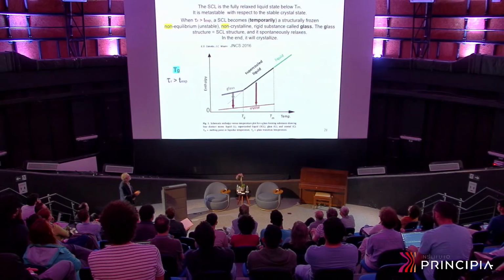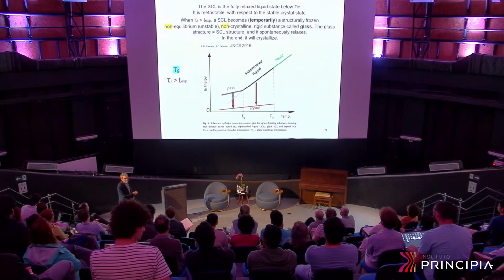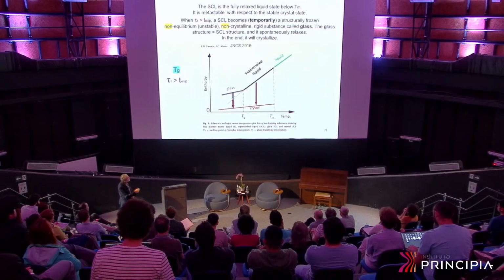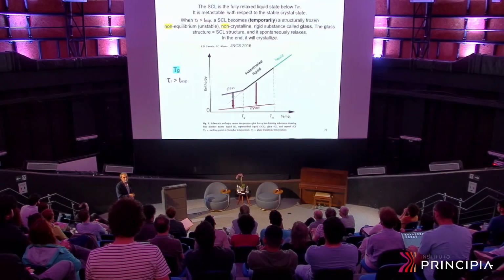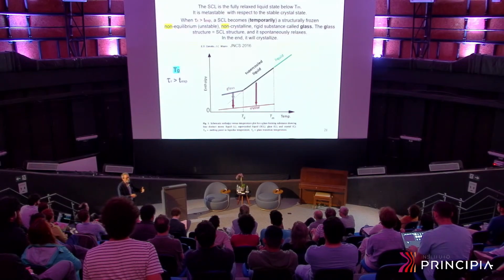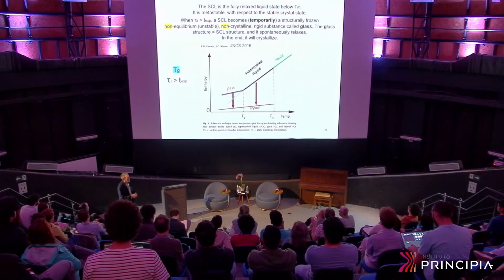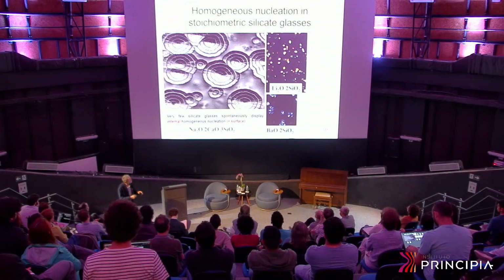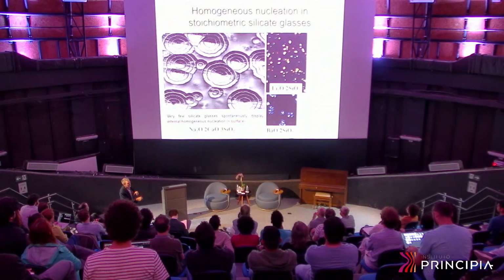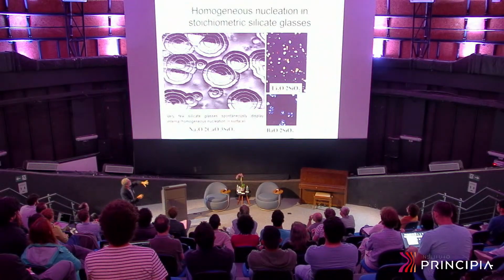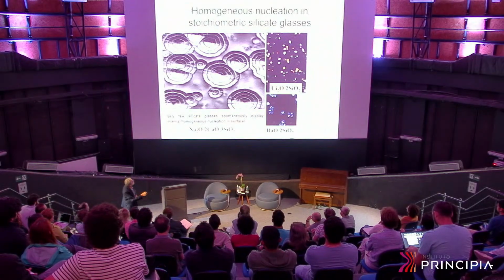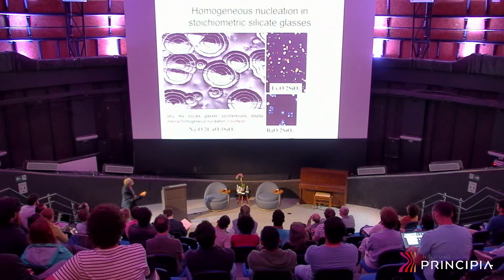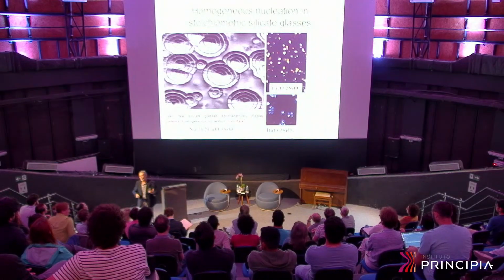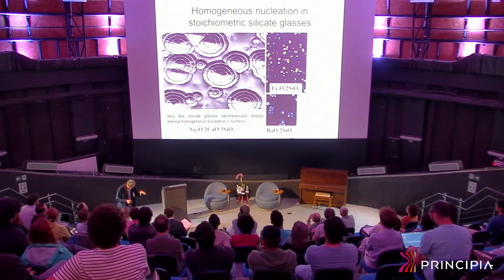Now I'm talking about making a glass by fast cooling, and then heating this glass and waiting until it starts to crystallize. That's the kind of experiments that you do. You first make a glass, and then you heat it fast and measure the nucleation rates. Okay, and this is the kind of microstructures that you get. See like the ring that's going on around. You see the black area is still glassy, and crystals start to form. So you can count these crystals with optical microscopy if they're micron size, or electron microscopy if they're nano size. But you can count this.